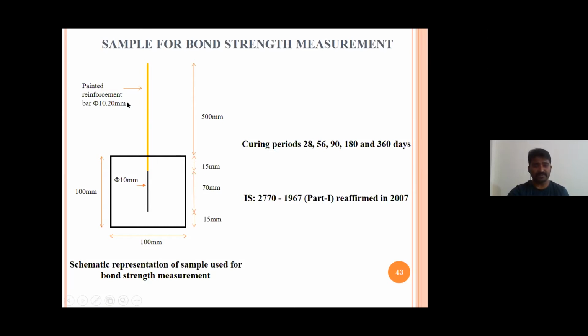This yellow part that you are seeing, we have painted the reinforcement bar with 20 micrometer paint. This is a corrosion resistant paint that we have used, as this paint is exposed outside to the environment, as we are very close to marine environment. So we wanted to protect our steel that might affect our engineering properties of steel concrete interface. So we have painted the steel with corrosion resistant paint, and even araldite was applied on the top so that there is absolutely no contact of environment to our bar. The main purpose of this is to avoid the corrosion of our reinforced bar.